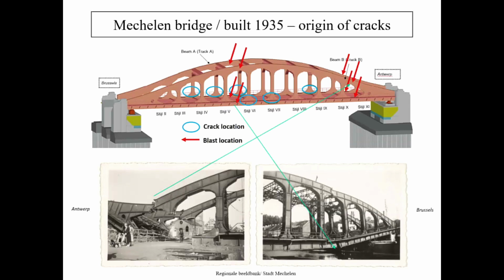Besides, all the computations indicated that the level of stress at the most critical locations was insufficient to initiate fatigue cracking. Fatigue computations showed that the fatigue life of this bridge after renovation can be extended safely for another 50 years till the 2080s. And this is somehow a testimony to the robustness of the Vierendeel railway bridges, even made with a poor quality steel. Then the owner decided to keep the bridge and restore it as he did for the two adjacent ones.